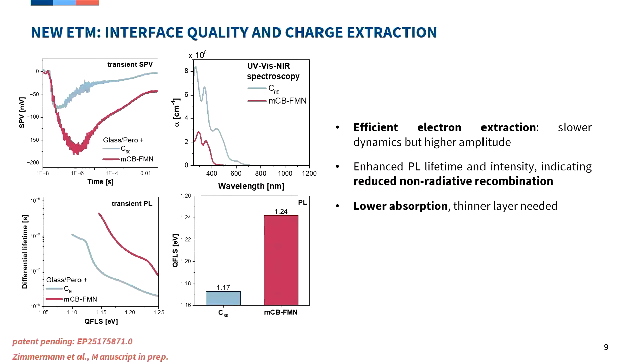Then what you see here in this bar chart is the quasi-Fermi level splitting, so that's the charges that remain in a solar cell with the one or the other contact, and of course that needs to be very high for a solar cell. With the new molecule, you don't have that PL quenching, so your solar cell is still a very good LED, which you want to have.